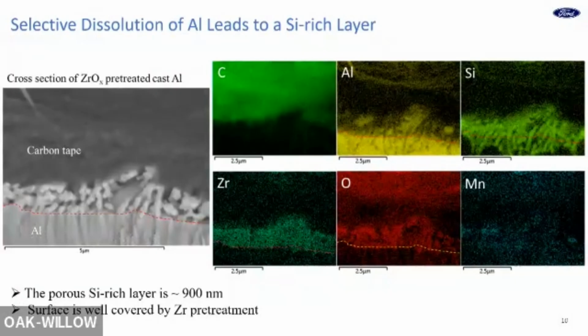There are mainly three interesting things from this cross-section. First, this layer is around 900 nanometers, and if you convert to the etch loss, it can be very high. The second thing, if you look at the silicon phase, you see this layer structure is continuous from the metal substrate, but the aluminum between the silicon is absent. That means there is some selective dissolution of aluminum during the alkaline cleaning process, which leaves a silicon-rich layer on the surface. The last thing is the zirconium. If you look at the zirconium distribution in the porous layer, it's pretty uniform, but limited by the resolution of the EDS, it's difficult to tell how the zirconium deposits on the surface: whether on the silicon phase or the aluminum phase or both phases.